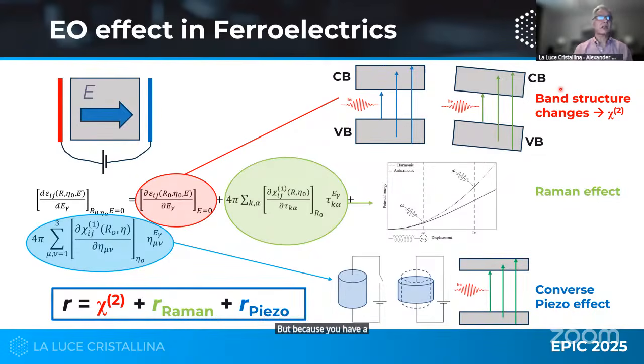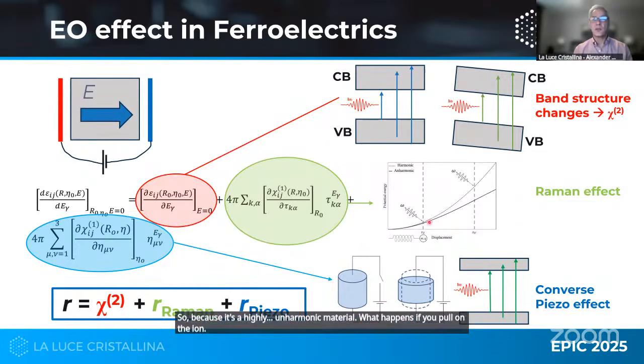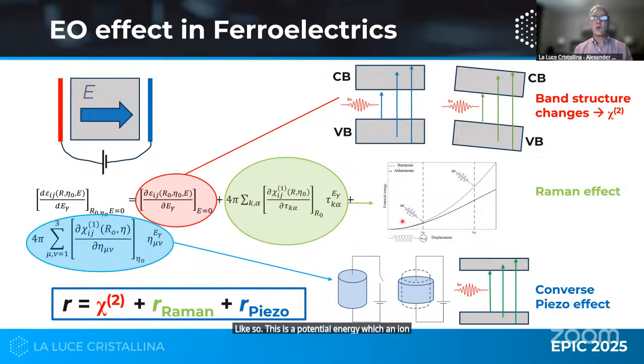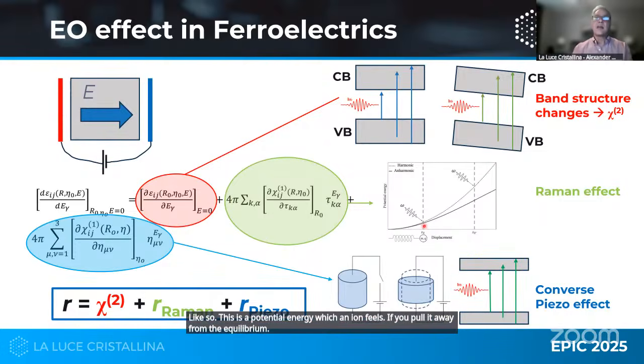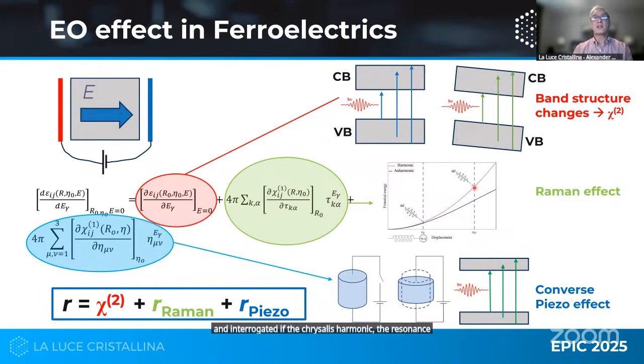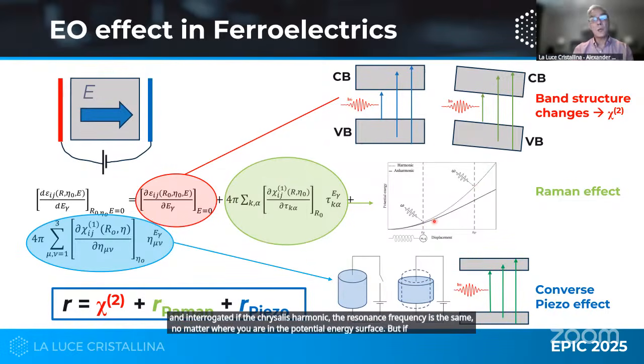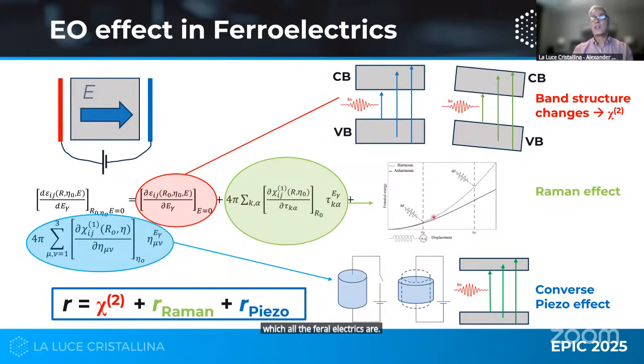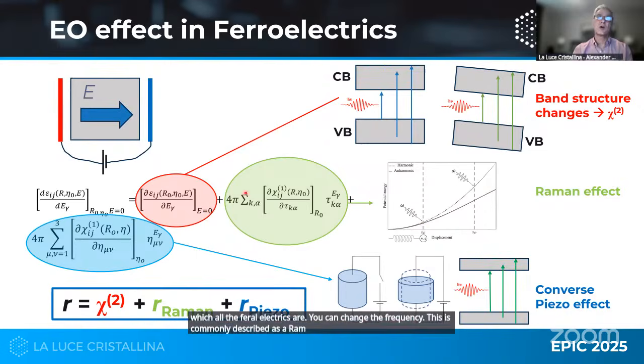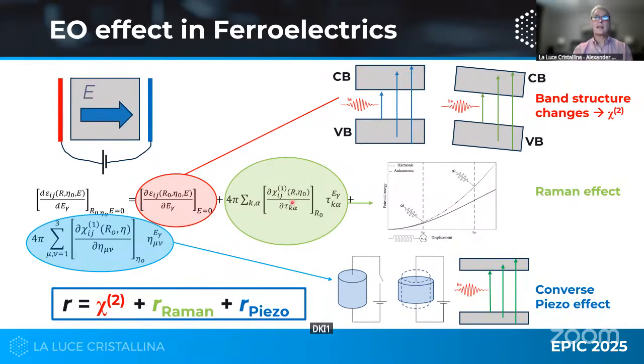But because you have a ferroelectric, two other effects contribute to the overall change of the refractive index. Because it's a highly anharmonic material, what happens if you pull on the ion, like so? This is the potential energy which an ion feels. If you pull it away from the equilibrium and interrogate it, if the crystal is harmonic, the resonance frequency is the same no matter where you are on the potential energy surface. But if it's anharmonic, which all the ferroelectrics are, you can change the frequency. This is commonly described as a Raman effect. And so this here, the d chi1 d tau, is the derivative of the susceptibility with respect to atomic displacement. That's a Raman susceptibility. And that is a very strong factor in the change in the refractive index.